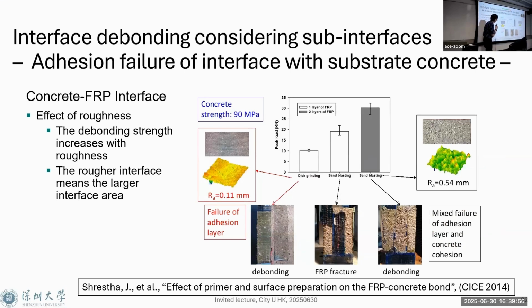Then this is the case. This is an external bonding FRP sheet case. Usually the debonding takes place in the substrate concrete. But when the substrate concrete strength becomes very high, like 90 megapascal, then the debonding takes place at the interface between the adhesion material and the substrate concrete. So if this is the case, roughness does matter. Greater roughness gives you higher bonding strength.